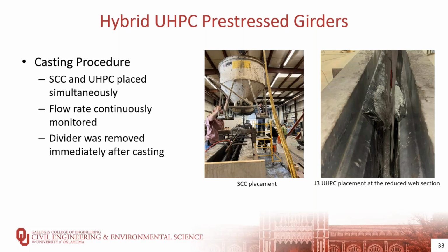These pictures show the casting process of the two concrete mixes. Both SCC and the UHPC concretes were cast simultaneously as we were trying to achieve the bifluid interface. So we started mixing the SCC first before mixing the UHPC. Then we started casting some of the SCC first from the end opposite to the UHPC, since a larger portion of the girder was designed with SCC, self-consolidating concrete.